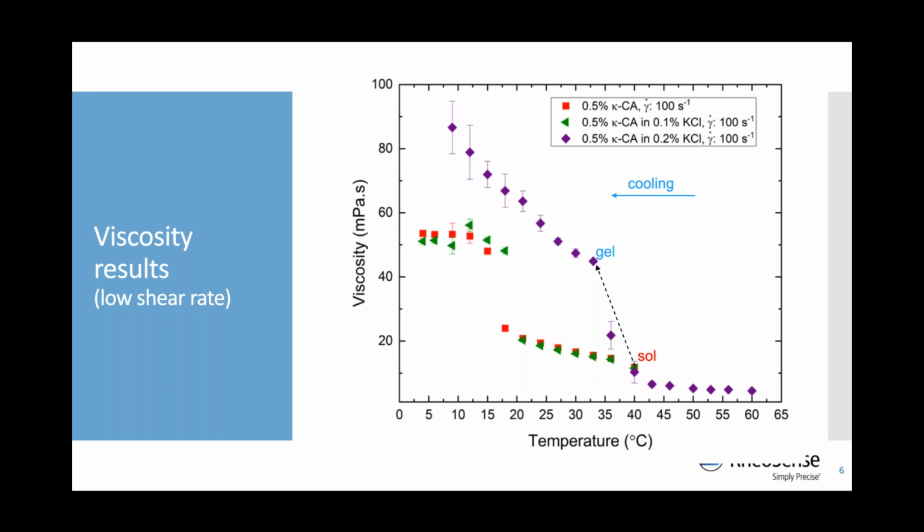of three-dimensional networks. On the other hand, the presence of salt, such as KCl, is an effective way in promoting gelation and aggregation of helical chains due to interaction between cations and sulfate groups in the crystal structure of carrageenan.